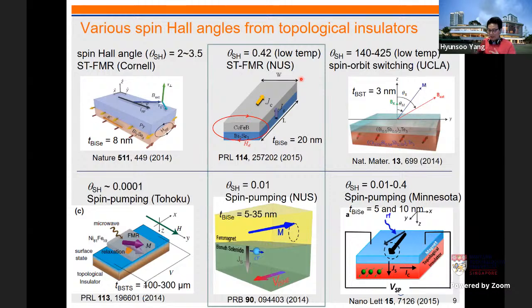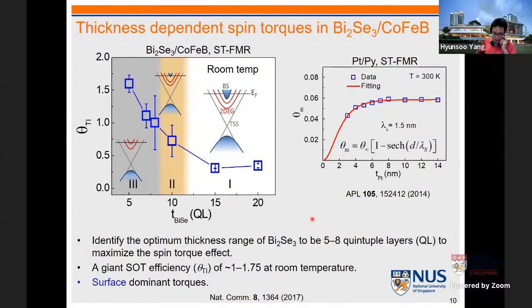So how do we understand these very scattered values from kind of similar materials? Of course, it depends on the measurement and detailed material properties and so on. So we try to understand this behavior by fabricating more systematic samples in one group. First, we noticed thickness could be key. So we made samples starting from 20 nanometers, 20 quintuple layers, then narrowed down to a few nanometers, and you can see the effective spin Hall angle increase from 0.25 to 1.6. So then we got to know thickness is very important.